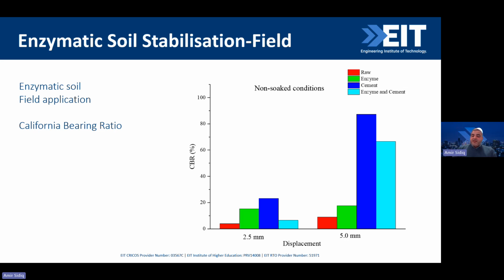Now that's why I wanted to know this, because when you're talking about the expansive clay, they actually experience significant swelling when they are immersed in water, soak condition, compared to non-soak. And that was my aim here, to understand: is this significant when we're using the additives, or is it not such significant? I clearly saw for the raw soil, it's actually doubled, but then for the remaining, it's almost remaining the same. So that was my idea, to understand the reason for the soak and non-soak conditions.